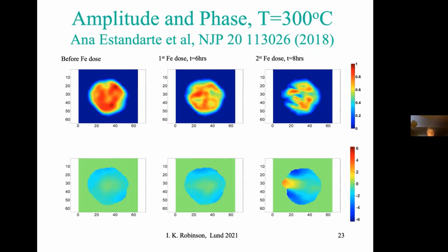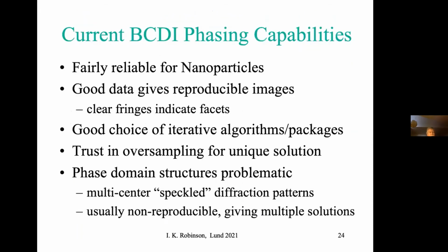I don't think we have to retract this paper or anything, but I think we can now give a better explanation as to where this distortion is coming from, where the iron is actually not dissolving into the crystal, but is actually staying on the outside and applying some sort of pressure on the surface of the crystal, and we see this response of the crystal to it.